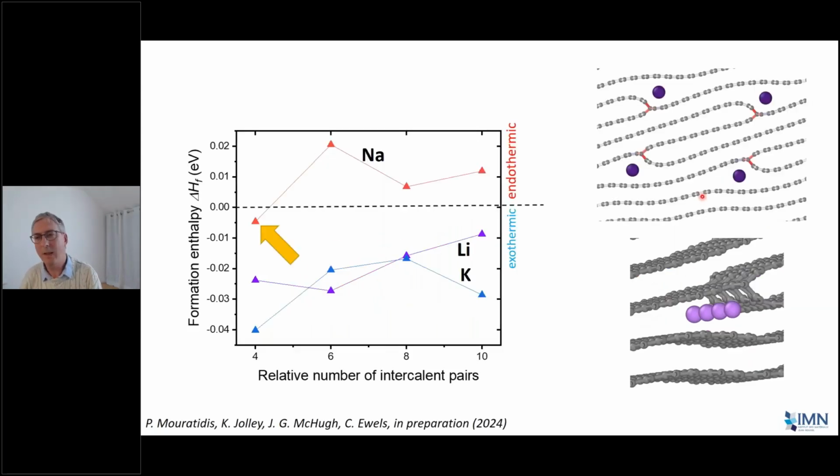But if we put a dislocation in, then locally the material is very low density, so there's more space in the lattice. And if we do calculations for that, we find that the sodium actually is stable along the core. So it looks like you can actually put sodium into graphite materials if there's a dislocation. So if we can control the dislocation density and behavior and type, then this might be a route towards using it to make better battery materials, for example.